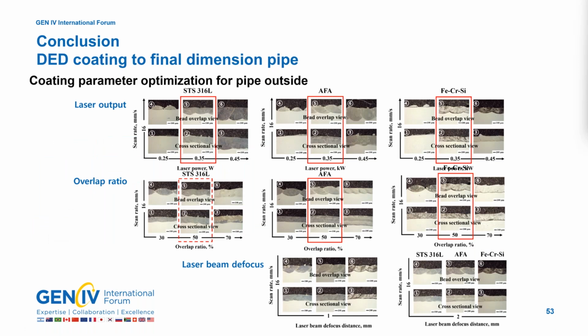Although the selected coating conditions for the plate substrate were used as a reference, additional parameter optimization was performed for tube coating to account for potential differences in cooling rates. The main variables were laser output, overlap ratio, and laser beam defocus. Due to the thin wall thickness of the tube, a laser power of 0.35 kilowatts was selected, while the other conditions remained the same as previously established.